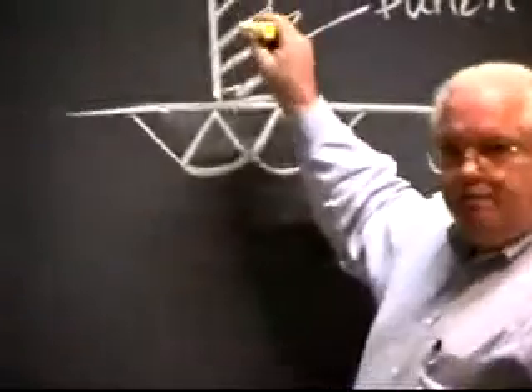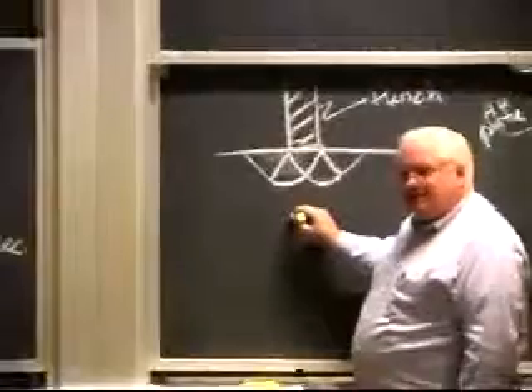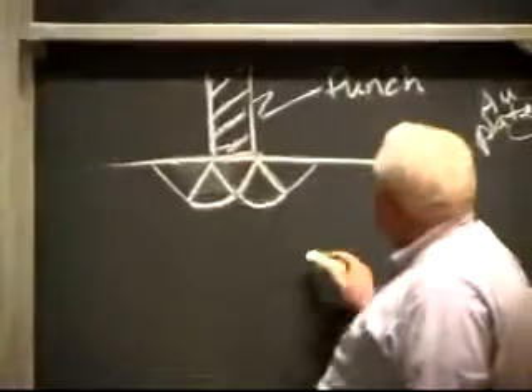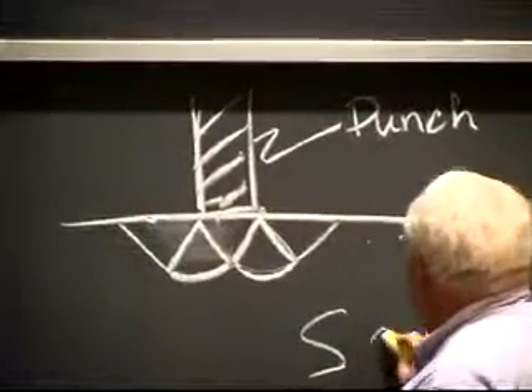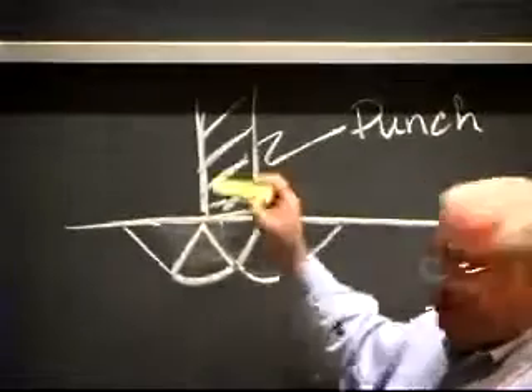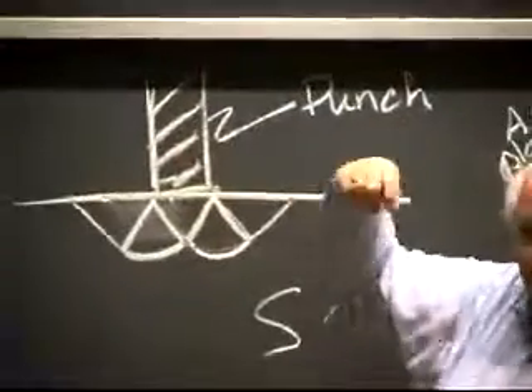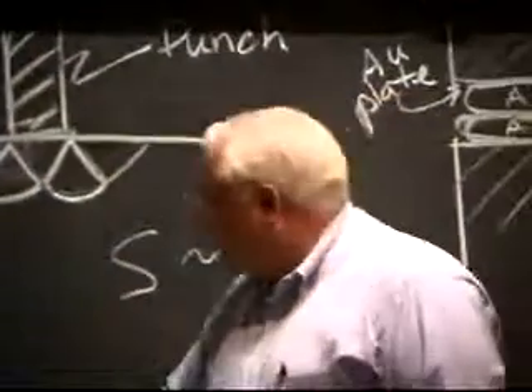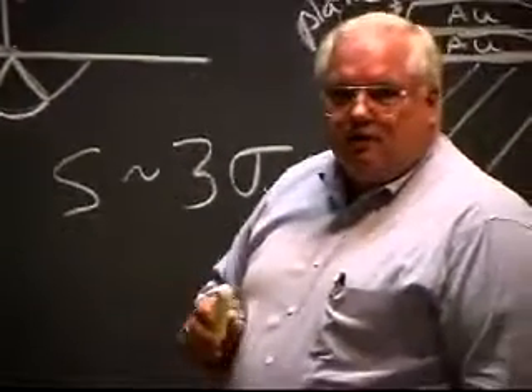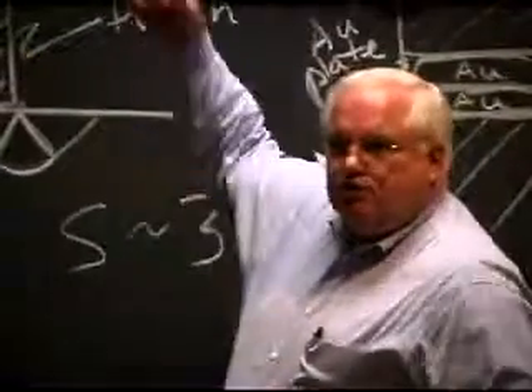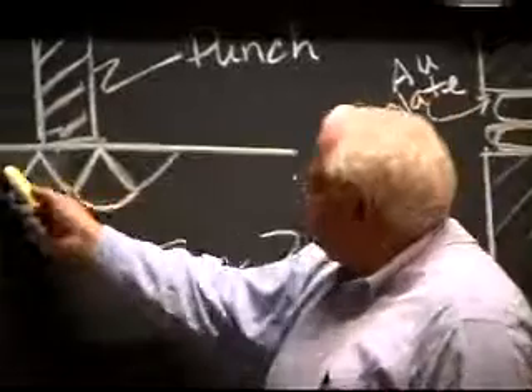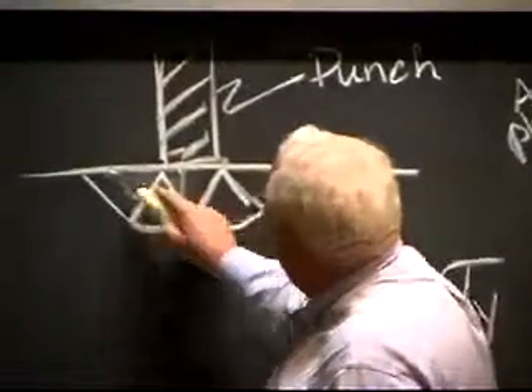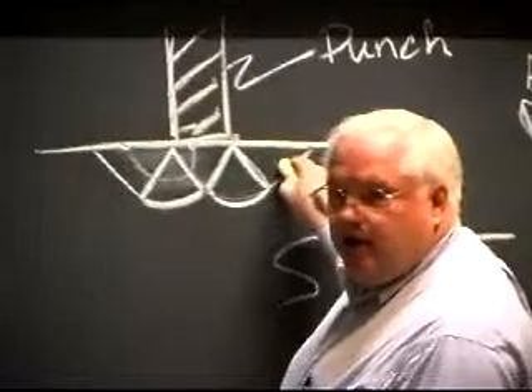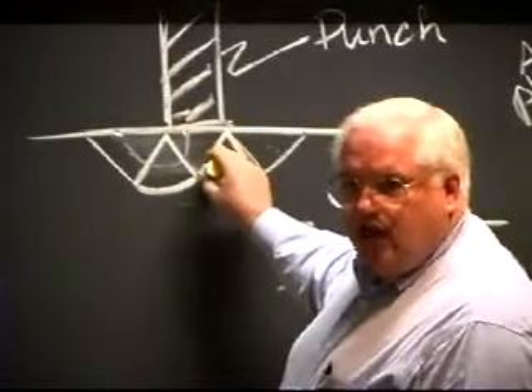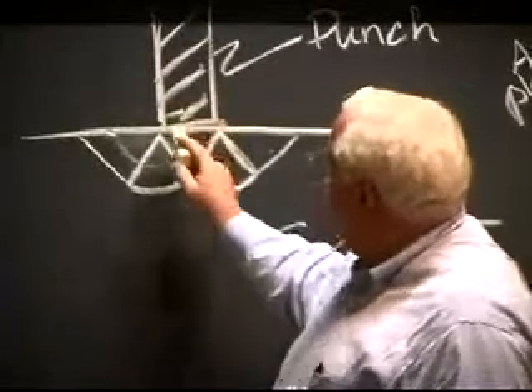However, if I have a punch, a surface asperity pushing against a solid object, it turns out that the indentation strength is about 3 times sigma yield. This is basically what we call a hardness test in metallurgy. You take a punch, a little pinprick, and you push it into the surface and you find out how deep it goes. Why does it take 3 times as much force to indent a big flat object with a small punch as opposed to 2 small things indenting things in equal area? Because the material here tends to have to push aside the material over here on the side, right? And the volume of material on the solid that's being deformed by this is about 3 times as great as the volume that's going to be deformed on the narrower punch.